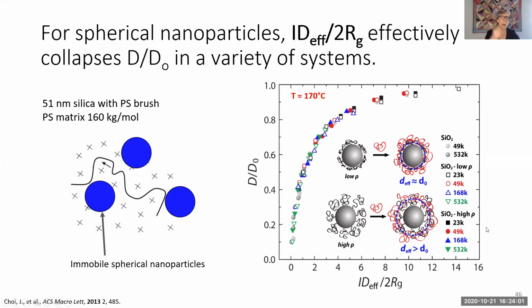The only tweak that we had to make to get this normalized diffusion coefficient to go as the ID over 2RG is to use the effective interparticle distance. And so that just means if you have a grafted polymer brush, right? So if you have this black grafted polymer chains on the particle, the diffusing species doesn't get all the way into the surface, right? Particularly when it's high grafting density, it can only get part way in. And so we used mean field calculations to give us this effective diameter. And once we use the effective diameter, which is bigger than the nanoparticle, once we use that effective diameter, calculate the interparticle distance, everything collapsed beautifully.